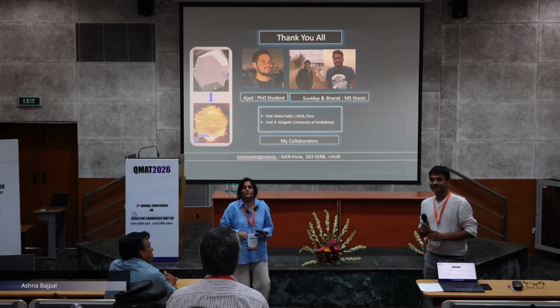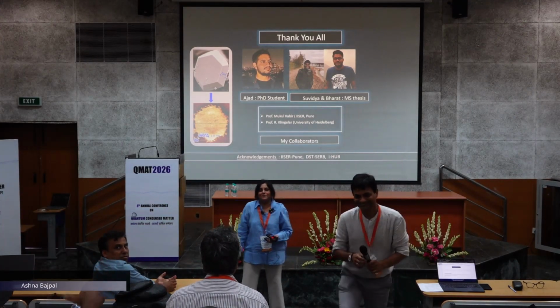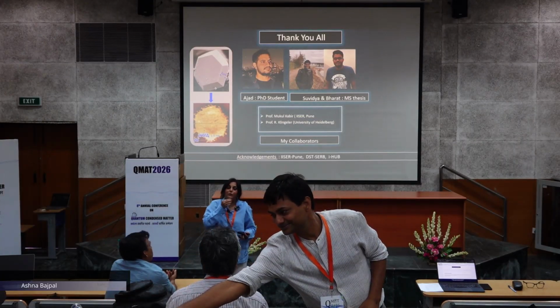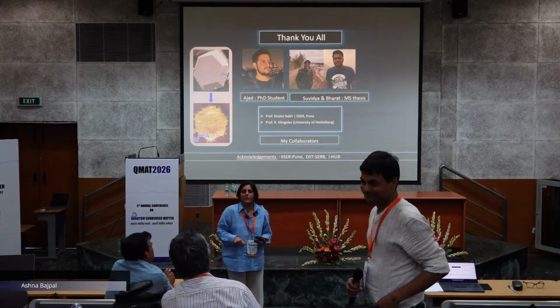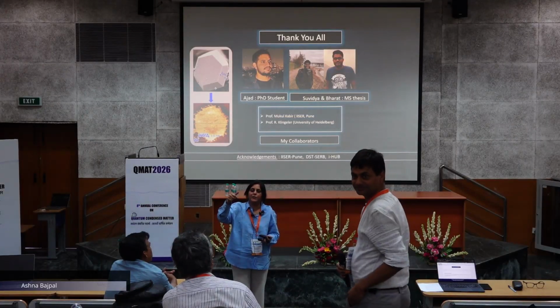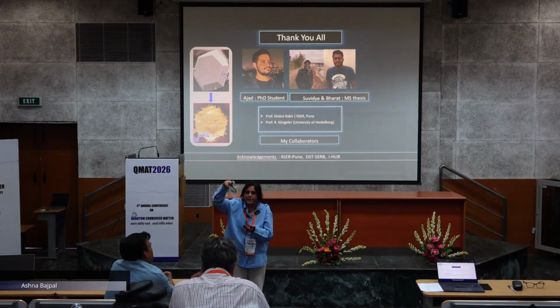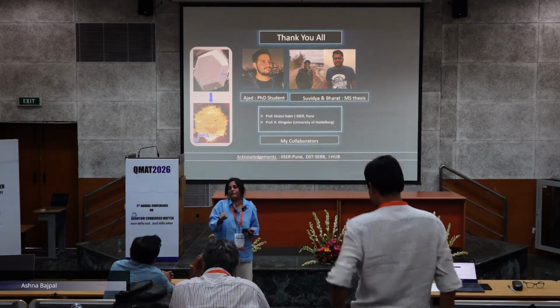Question? How does the magnetism change with doping of a non-magnetic entity? So, even with lithium doping, lithium and calcium are basically doing strain. You are basically playing with the octahedra around the magnetic atom, and still the magnetism changes significantly.